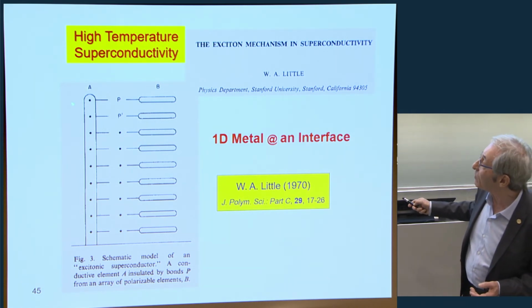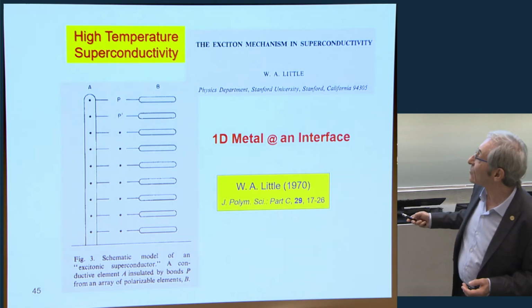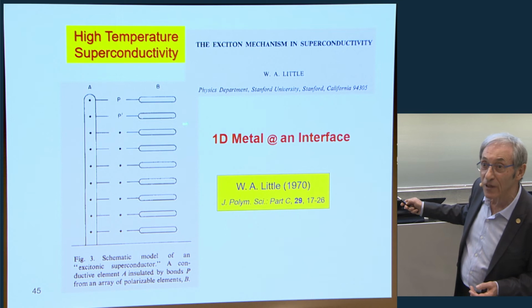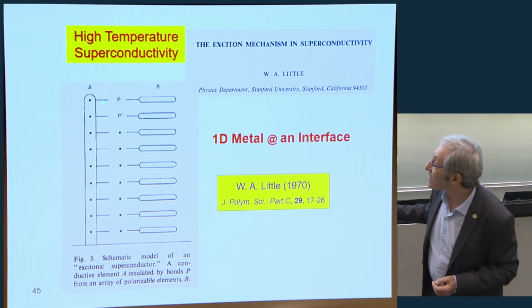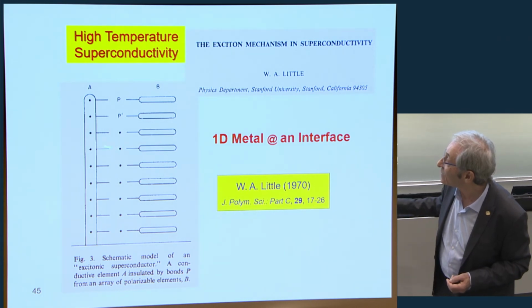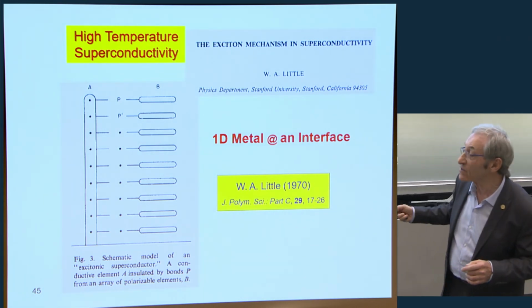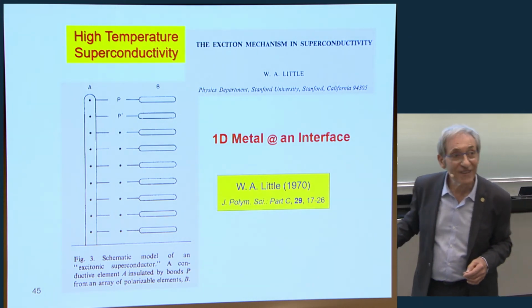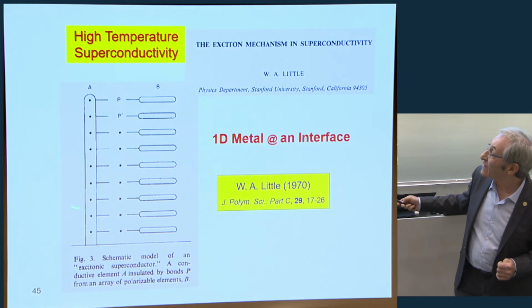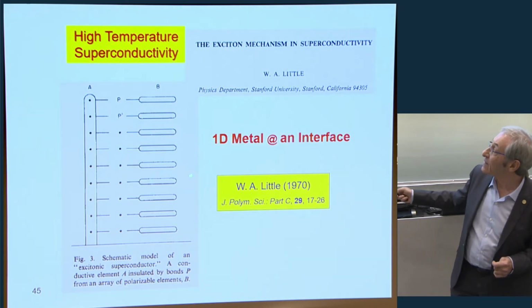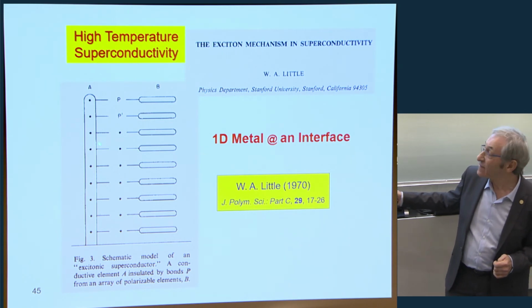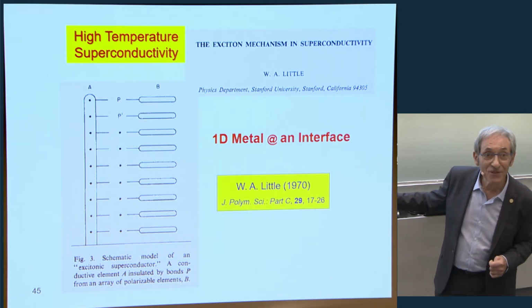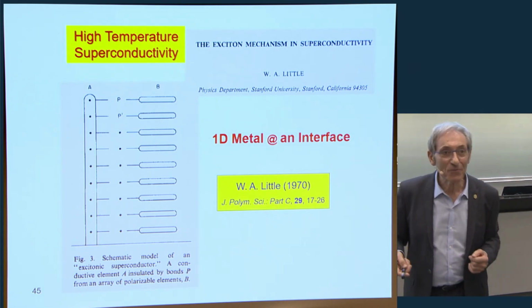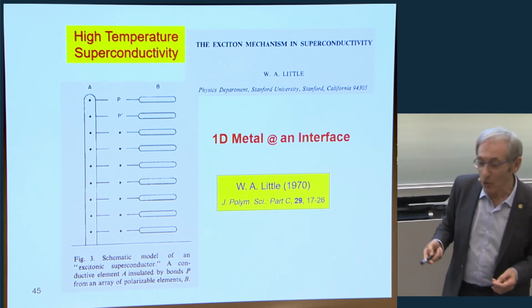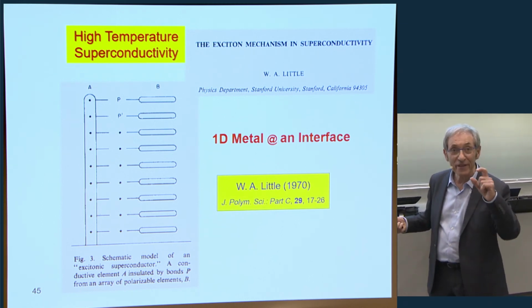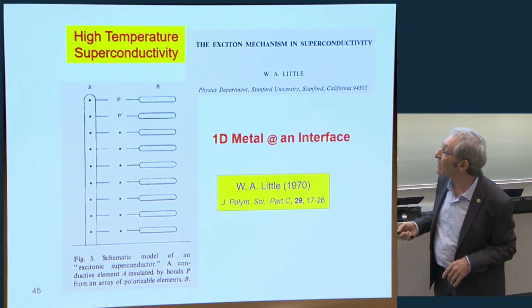So he proposed that if you bind to this one-dimensional conductor polarizable molecules, but separated from the conducting line at small distance, so that there is no electrical cross between the two, then the electrons flowing here repel electrons in these groups, and then positive charges attract the next electron. And this is, in a simplified manner, the proposed mechanism of coupling between electrons to make the Cooper pairs along the one-dimensional metal.